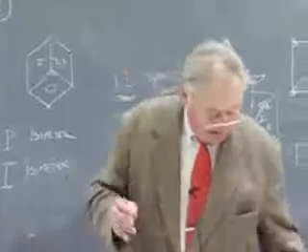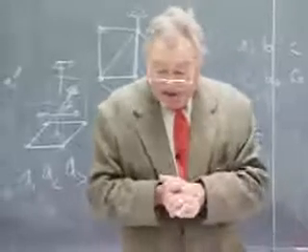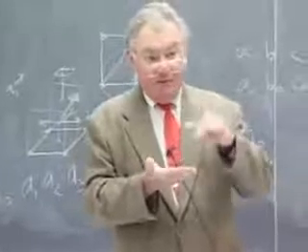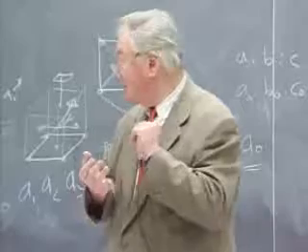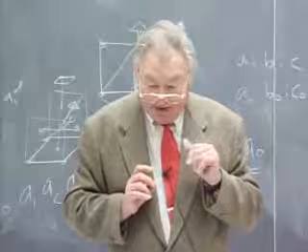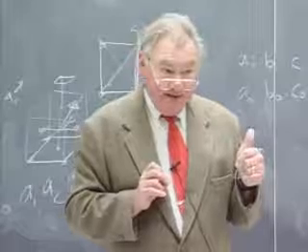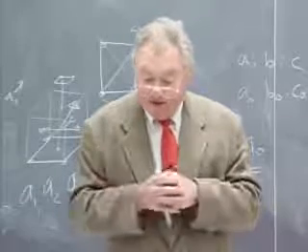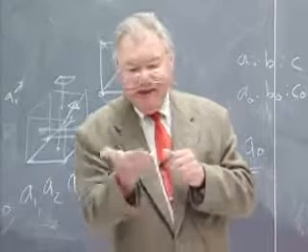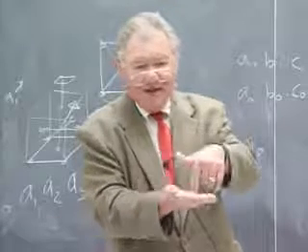And you might think that we really have an enormous amount of work to do. We haven't considered any symmetry combinations that involve a horizontal mirror plane. For example, we looked at what symmetry 2 requires, and we found the primitive monoclinic lattice, the side-centered monoclinic lattice, and the body-centered monoclinic lattice. So there's more than one lattice type into which we can drop a given point group. But what would you have if you had a mirror plane perpendicular to the twofold axis? What kind of lattice will that require?